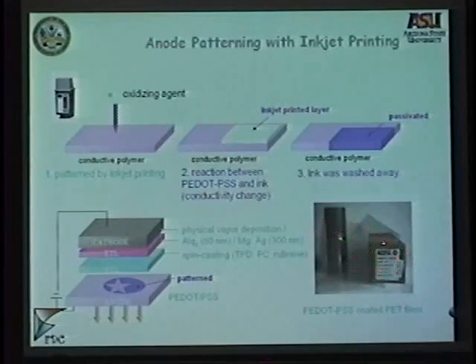They are like miles and miles long, they sell more than 30-mile long substrates. But they give us the rolls, and they also cut them, they're very nice, they cut them into European size paper so that we could feed them in the inkjet. So this is basically plastic PET that has PEDOT coated on it via roll coaters. The PEDOT:PSS is about 150 to 200 nanometers thick. So we take the sheets and put them in the inkjet printer. We take the cartridge and clean it out, but HP gives us clean cartridges already, so that helps a lot.